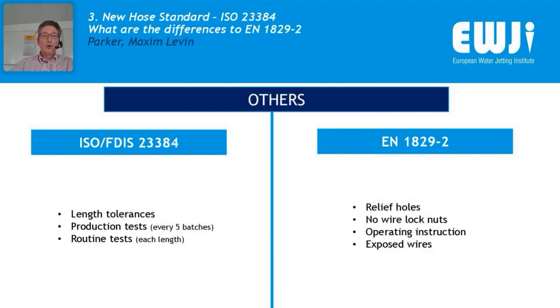A few other things which are resulting from a little bit different targets of those standards. For example, in EN there are some additional safety requirements, like you have to have relief holes on the nuts, no wire lock nuts shall be used, you have to supply operating instruction with every hose assembly, and so on and so forth. Also quite an important requirement that the hose assembly with exposed wires shall be removed from service.